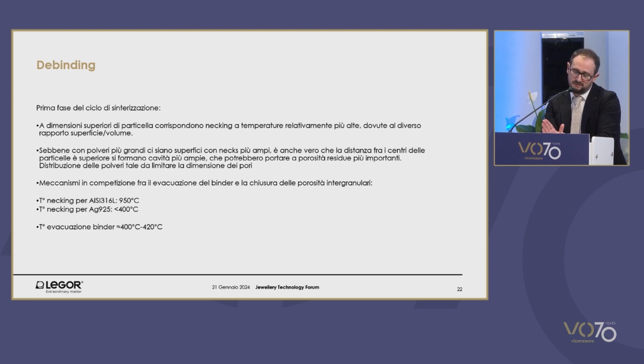So the two competing mechanisms in the debinding area, that is, the first part of the cycle at high temperature of the sintering process, derive from the fact that for some alloys, for some powders, the debinding process takes place at much lower temperatures compared to the beginning of powder aggregation. This is the case of AISI316L, where the necking temperature is 950 degrees, whereas the binder evacuation temperature, which lasts several hours and takes place at 400 degrees, is not competing against the first phase.